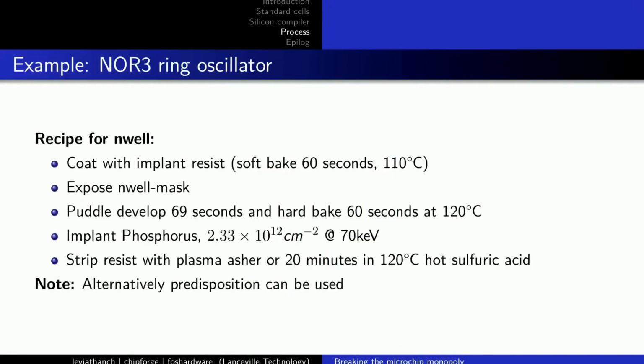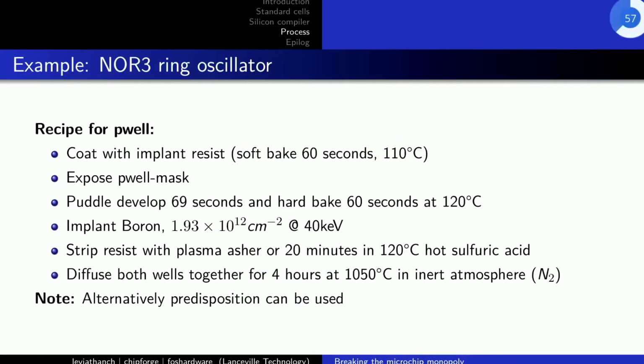So the recipe is easy. First coat, expose, implant, and then resist strip. Same for the P-well. And after the resist strip, you can put it into a diffusion furnace in inert atmosphere for 4 hours.